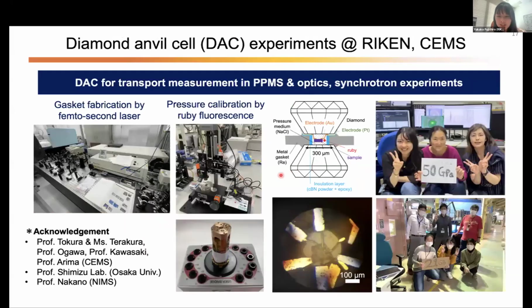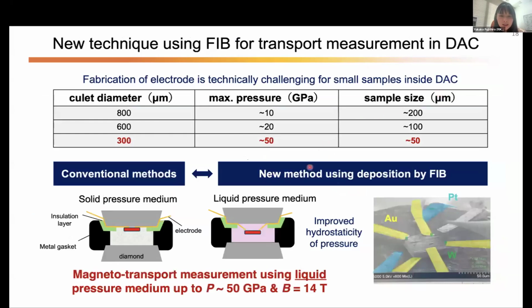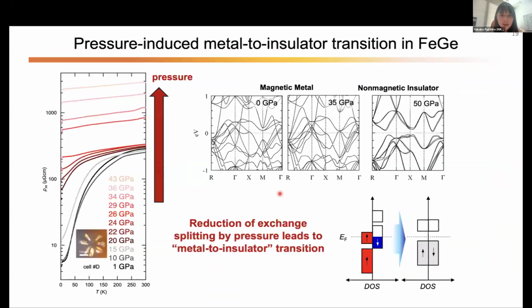So I would skip the detail, but we recently built a measurement setup for the diamond anvil cell, which can be measured in a PPMS and also with optics. And we also performed synchrotron experiments. And as you already know, it is very difficult to measure precise transport under high fields because the sample size is very small. But we used a very original focused ion beam technique to fabricate the electrodes one by one like this, and successfully measured the transport using a liquid pressure medium up to very high pressure.